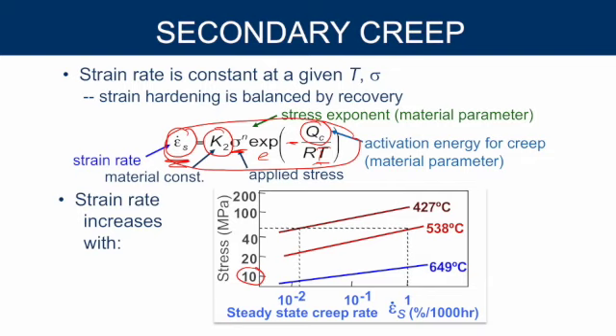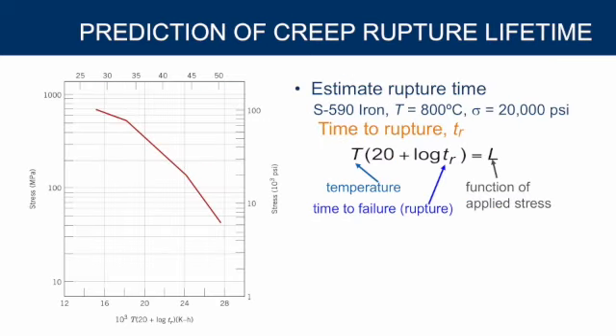So if we want something to strain or fail in creep, if we heat it up, it'll strain much quicker. Okay, so let's do an example of that. Instead of using the calculation, a lot of these materials have been tested for creep, different types of iron, different types of steel, alloys, and they create tables that essentially take the exponential result and graph it so that we can just read off the numbers that we're looking for with respect to temperature, rupture time, and stress.